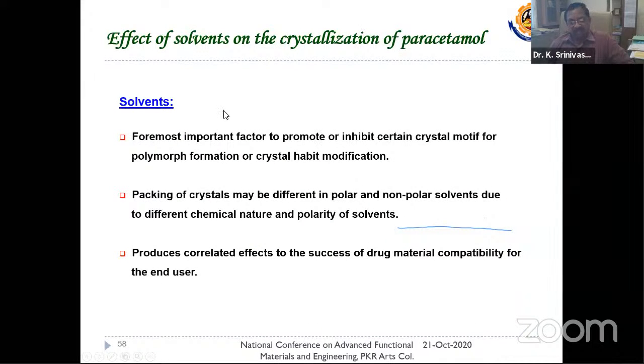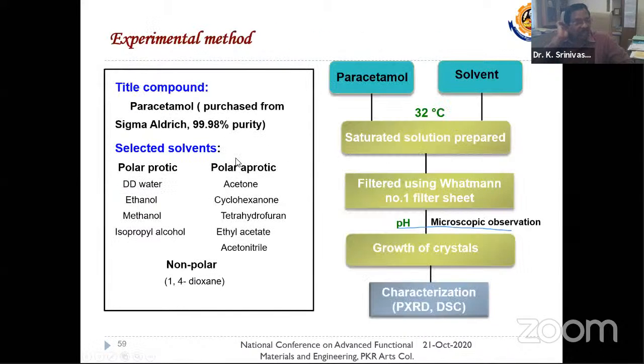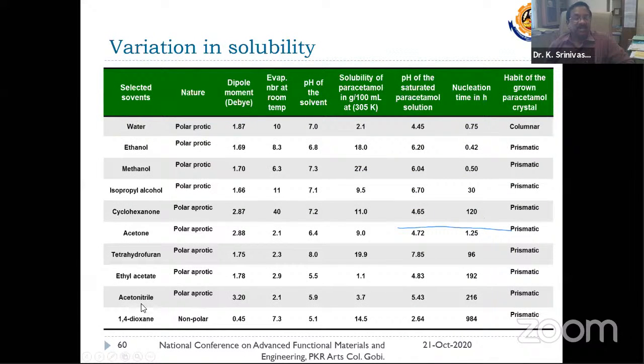And so we employ different solvents to grow them into bulk. Of course, by anticipating different polymorphs, we used different kinds of solvents. Every solvent has its own effect on the growth. We used different polar aprotic solvents and non-polar solvents, prepared the solutions and filtered them, then the usual growth process. These are the list of solvents selected, from water onwards, with polar nature, dipole moments, evaporation rate at room temperature, the pH of the solvent and the solution, the solubility, and the nucleation time, the time taken to get the first speck of solid from the saturated solution after the saturation condition is achieved. These are all the morphological aspects.